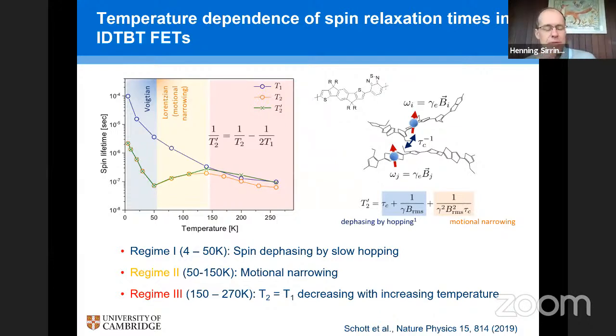When they're sitting on a particular site, they see a local magnetic field orientation, which is determined by the combination of the external field and also the hyperfine fields that the charge sees locally. And then the spin precesses around these local magnetic fields. And if they're hopping slowly, the spin dephasing becomes more effective at higher temperatures, as the charges hop faster to sites that have a different local field orientation.